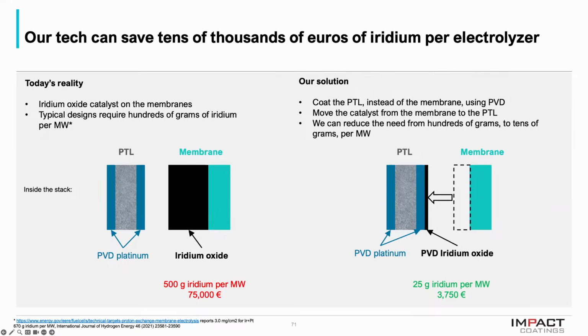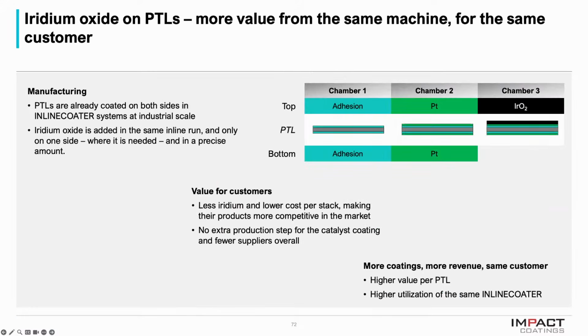So the opportunity here is actually quite simple. We use less iridium, we can use it more efficiently, and of course we want to combine it with an industrial manufacturing process. And that's exactly what we're targeting here by placing the iridium oxide on the PTL using the INLINECOATER. We're already coating PTLs at industrial scale today, with platinum. In the cartoon here, you can see that we have 3 coating chambers. We run an adhesion, we run the platinum deposition, double-sided. And then in the 3rd chamber, we can add the iridium oxide, but only on one side where it's needed, and we only add it in a very, very precise and tiny amount.